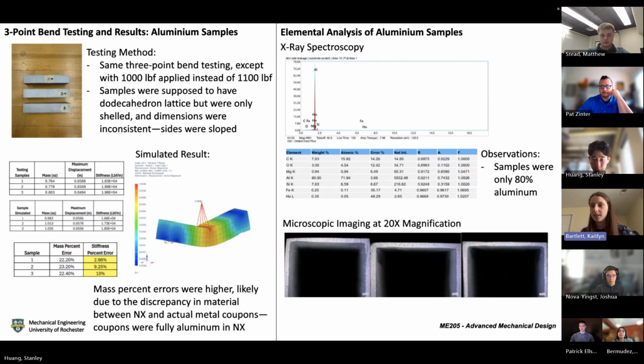The highest were carbon and silicon, at 7.8% of the weight. We had to take that into account when comparing the simulation versus the tested coupons, because in NX it's fully aluminum. It's the idealized model.